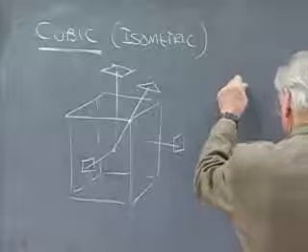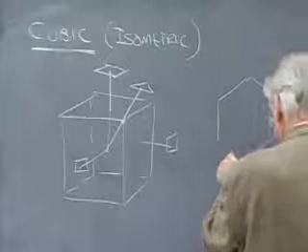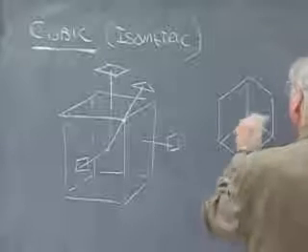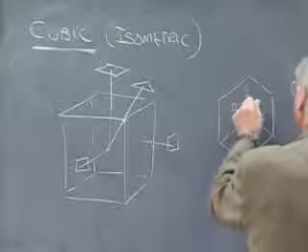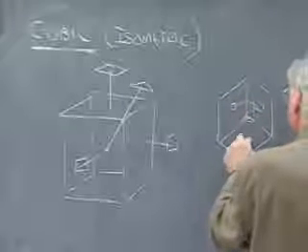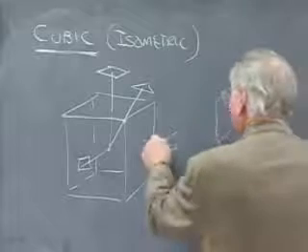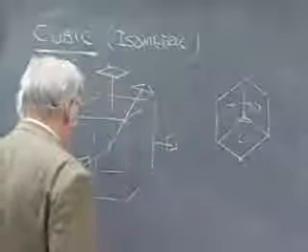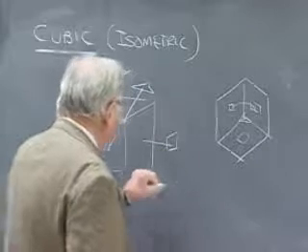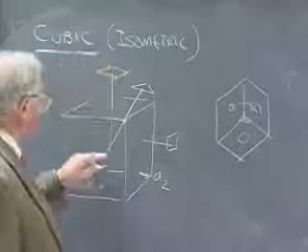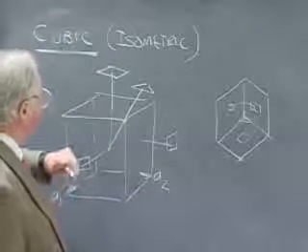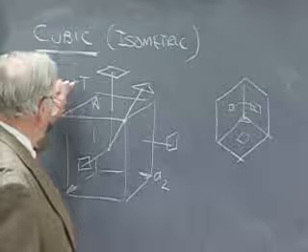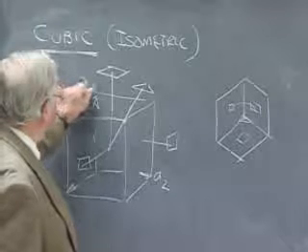We've seen that if I look down along the diagonal of an equiaxed tetragonal prism, the threefold axis takes this face, rotates it into this face, and rotates it into this face. So I'll have to have a fourfold axis coming out of every one of the faces, and having that arrangement of fourfold axes means that not only will the two translations be identical in the base of the cell, as is the case for tetragonal, but if I put in that threefold axis as an extender, all three edges of the cell have to be identical by symmetry.